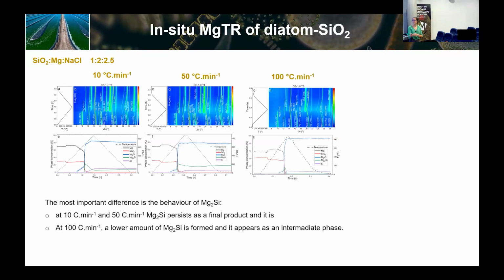And what we think is the reason for that is that this magnesium silicide that is being created, if you see also here, the amount is much higher than when we heat faster. This magnesium silicide that is formed as an intermediate, this layer starts to become thicker, and then it also makes it difficult for the magnesium to further react with the silica. But if everything goes faster, then the magnesium silicide phase will be thinner, and then you can have more reaction proceeding.